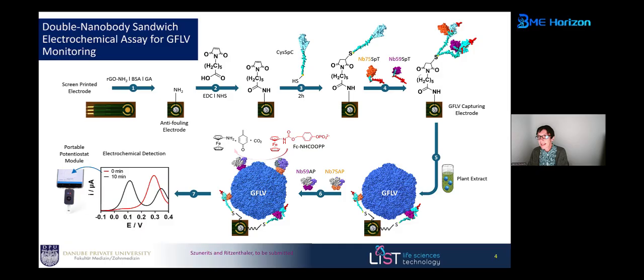So what we also show here is that with the type of chemistry we're using, we can also put multiple bioreceptors on the surface. This is particularly interesting if we go to virus sensing or bacteria sensing, where we always know that there is a mutation in the outside proteins, which we often target for viruses. So in our case, we overcame mutation in this plant virus by adding two bioreceptors on the surface. And to dig a little into the bioreceptors, I talked about antibodies, very often used in ELISAs and electrochemical sensors. Here, we took the choice of going away from antibodies and using nanobodies. That means it's the very small binding end of an antibody. It's around 4 nanometers in size.